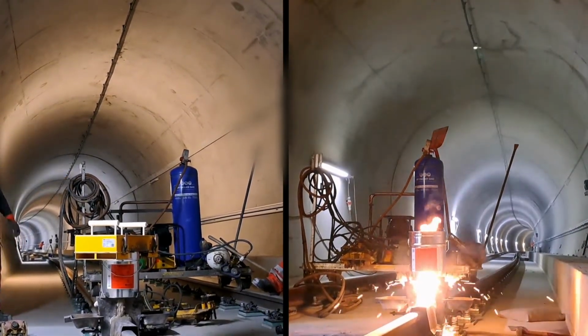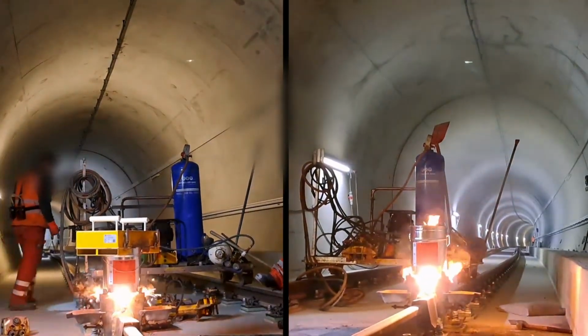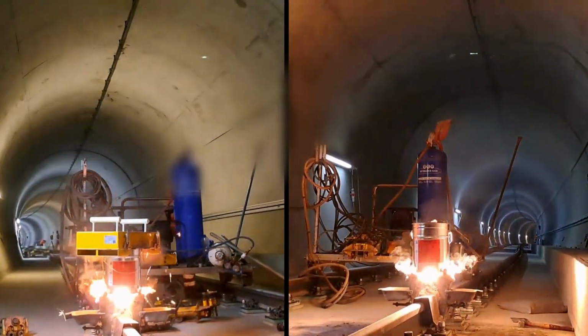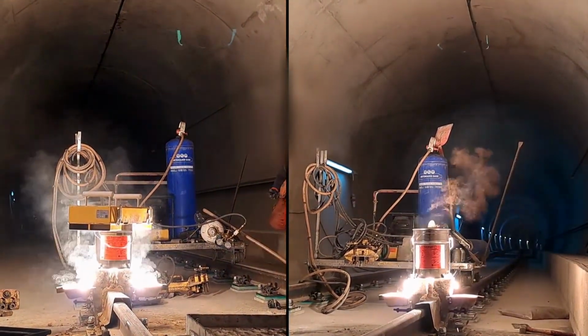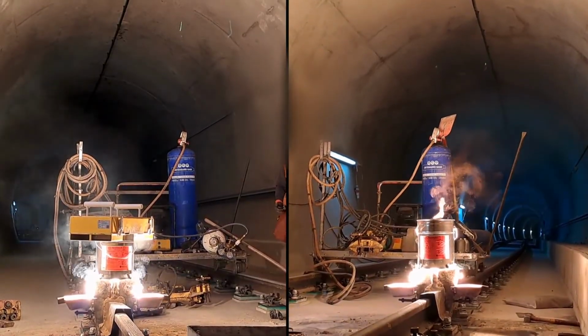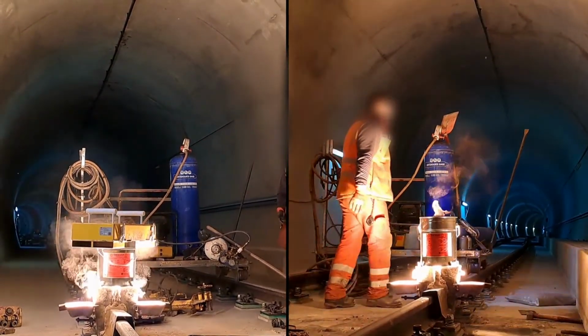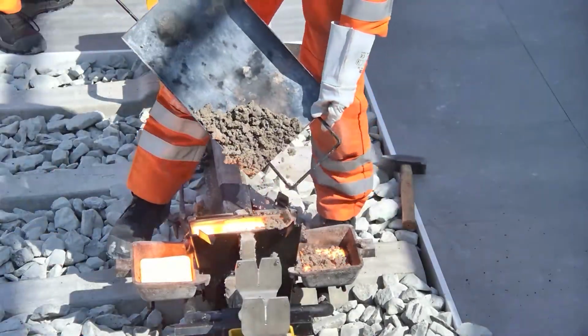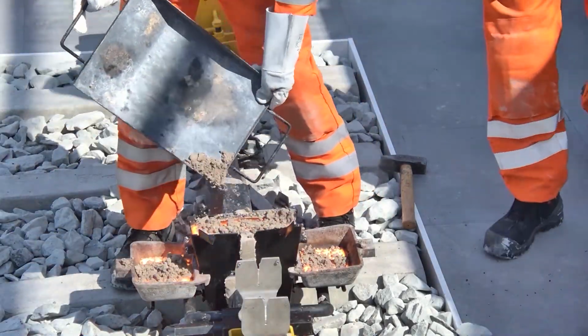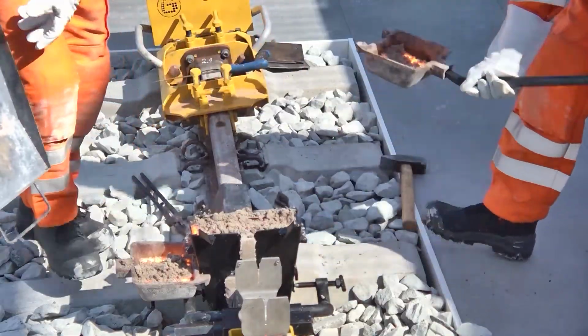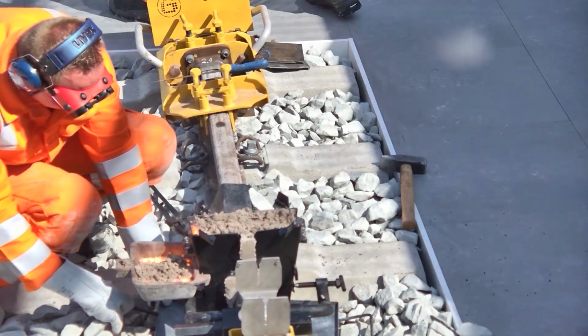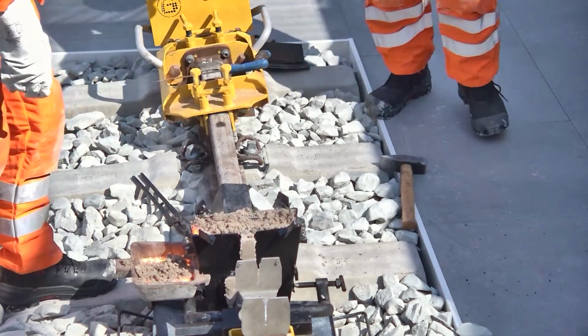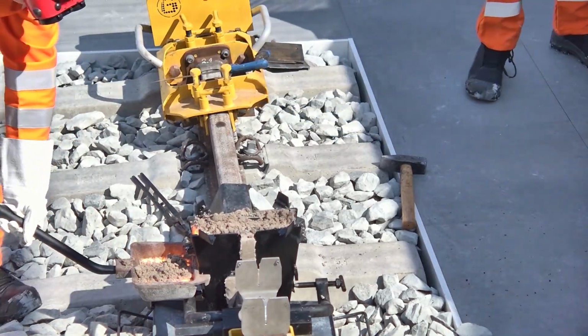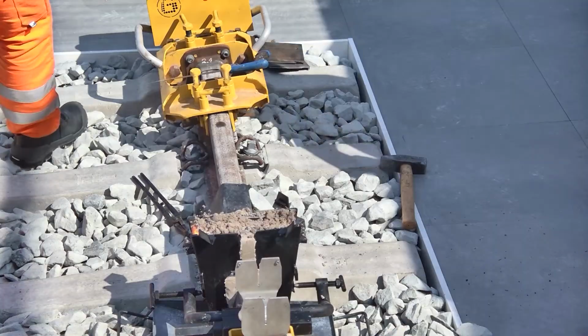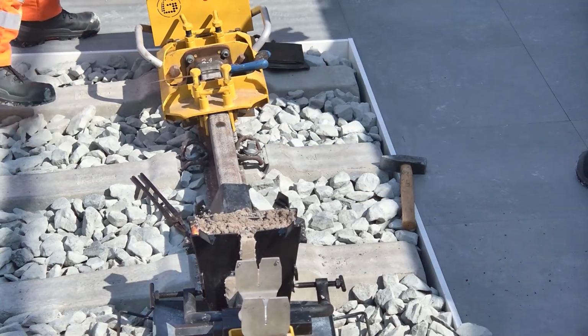As you can see, the EnviroFilter that we put on the weld filters all the exhaust gases from the reaction, both from the crucible that would exit the crucible, but also from the reaction, and make sure that you don't see anything, that you don't smell anything, and that's just the cleanest possible way of performing an aluminothermic weld. We can use the filter cartridges for about 20 welds, and then they get to be replaced.